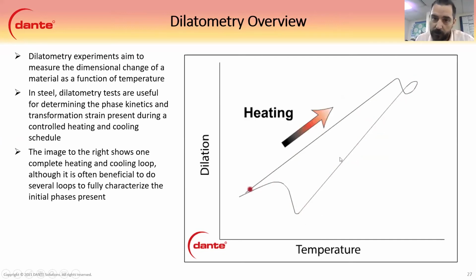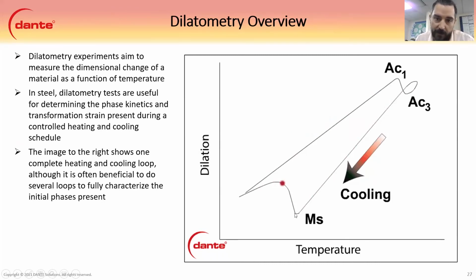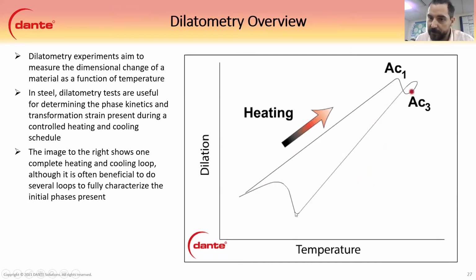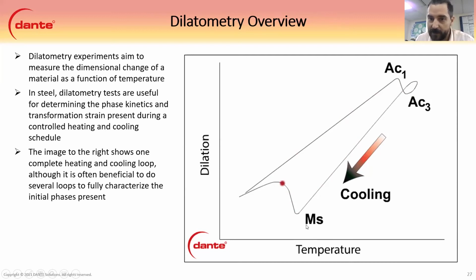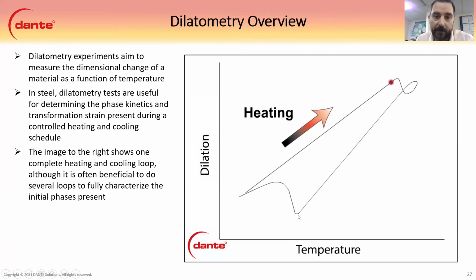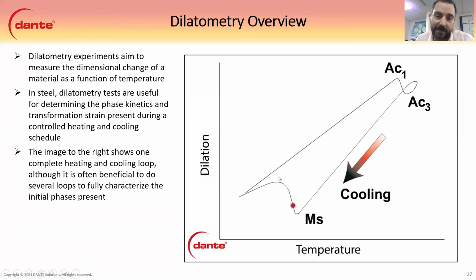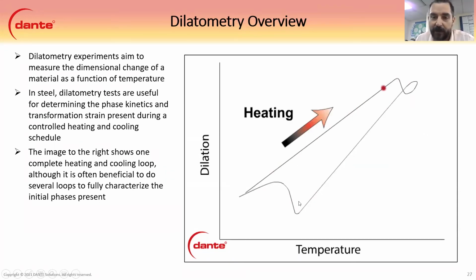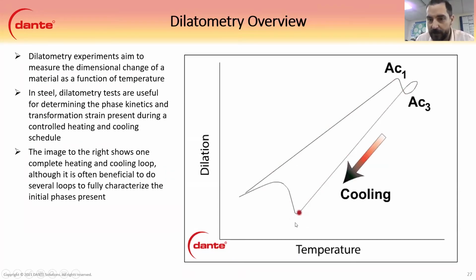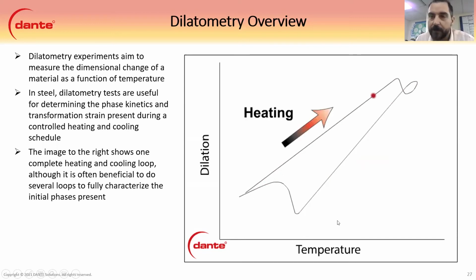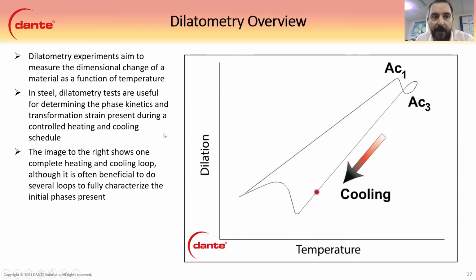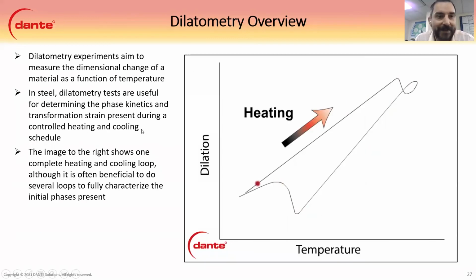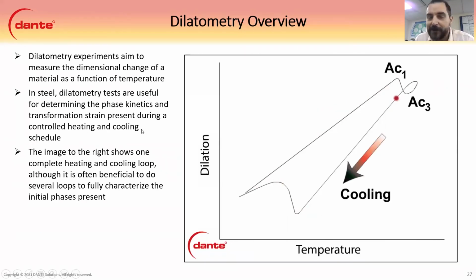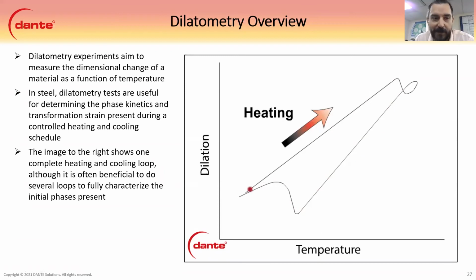And then you start to cool after that, right? And then you cool as you're quenching. And when you see one of these changes down at the bottom here, where the Ms pops up, you see a change in dilation. That change in strain is a phase transformation. And we get a lot of good data on that. So what temperature it started, how much is the whole strain, and everything. And in steel, these tests are really useful to determine the phase kinetics and the transformation strains.